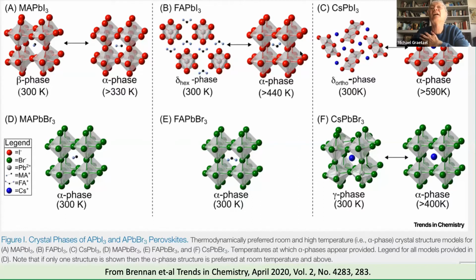It's optoelectronically superior to both methyl ammonium and cesium, but it has a big problem. It's not stable at room temperature. The black phase reverts to a yellow, hexagonal phase, which is not active at all photovoltaically. On the contrary, if you have the yellow phase, it will actually decrease the efficiency of the device by promoting recombination of carriers. So a lot of people are focusing on this phase now. For single junction, that's certainly the best choice you can make.